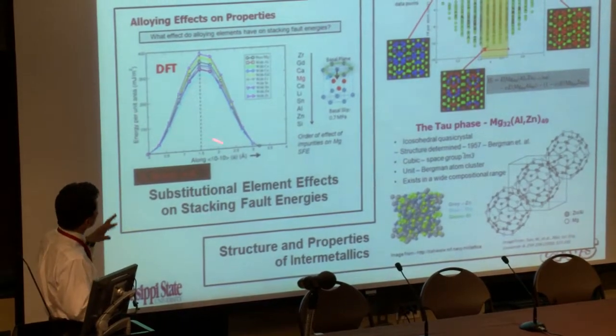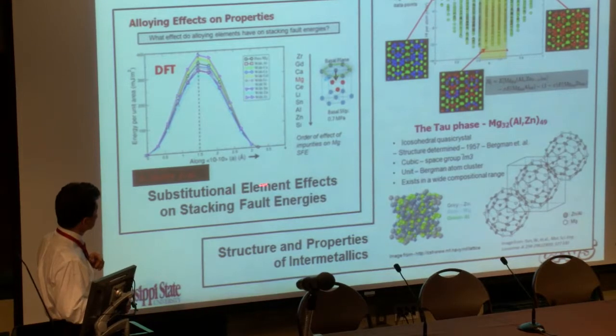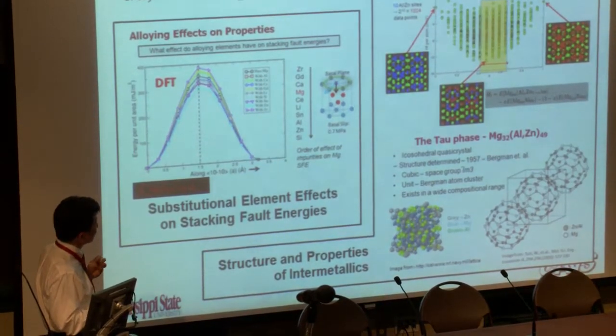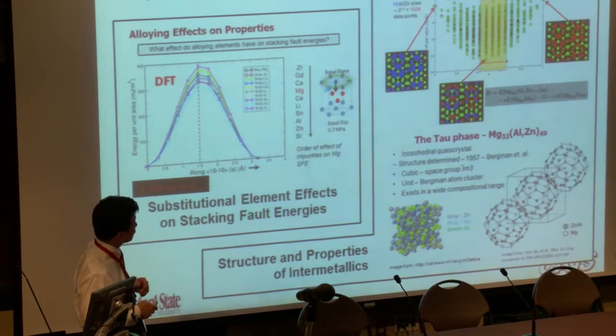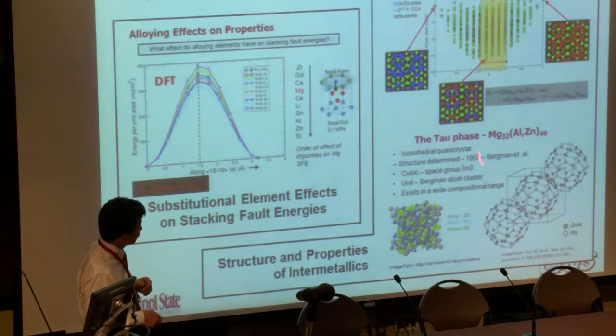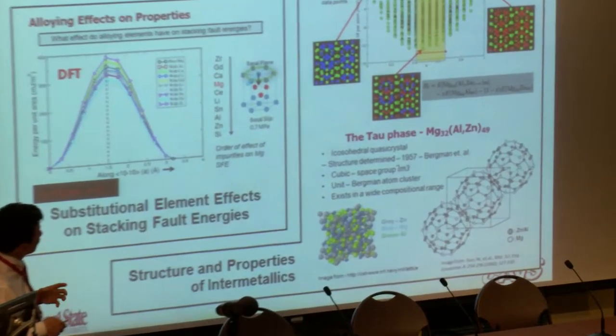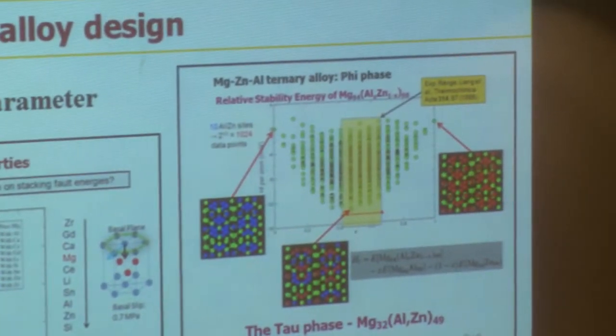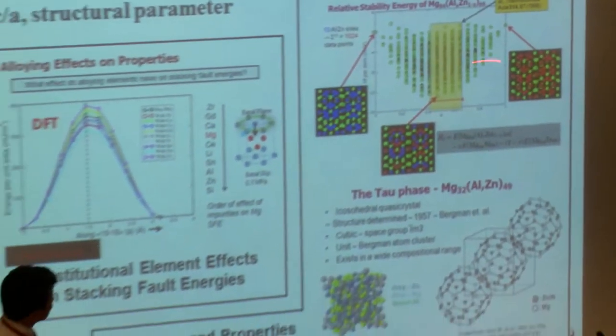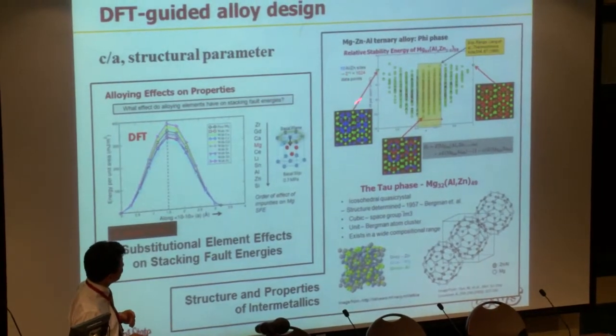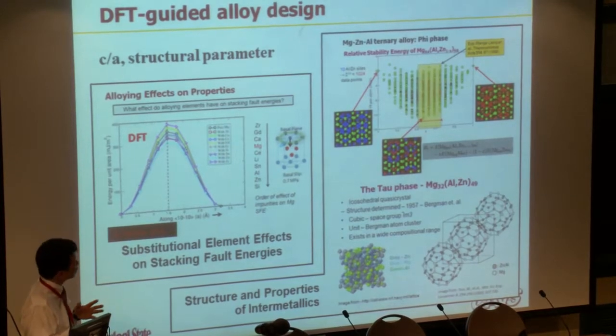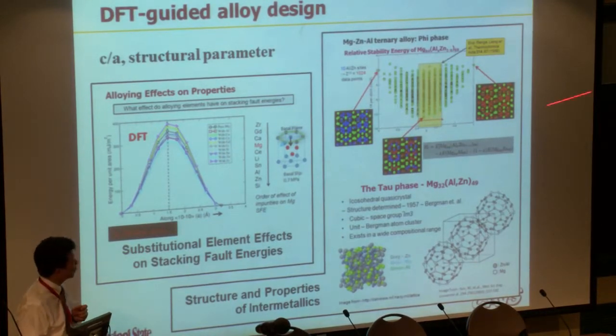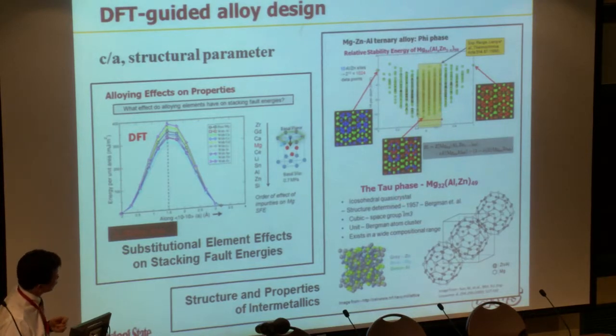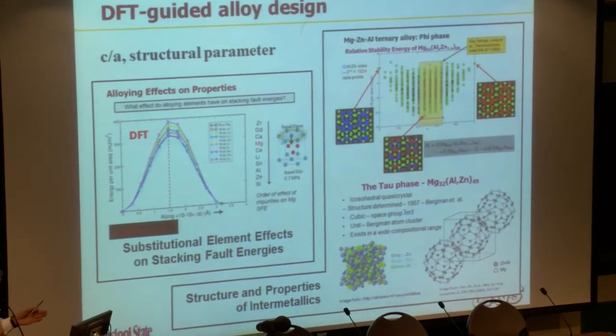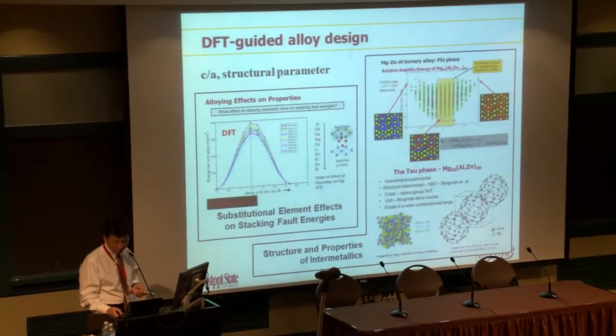And then in the meantime, the physicists are looking from the dislocation point of view, looking at magnesium and its interaction with the different elements, and seeing how the stacking fault energy is going to impact the slip system. But also, working with Northwestern, Greg Olson, their experiment couldn't identify the aluminum and the zinc positions. So we use DFT to run about 10 different positions, about 1,000 numerical simulations, to look at what is the most favorable and stable energy location, what the configuration is of the two different phases. So that gets into the design as well as the thermodynamic phase diagram information.